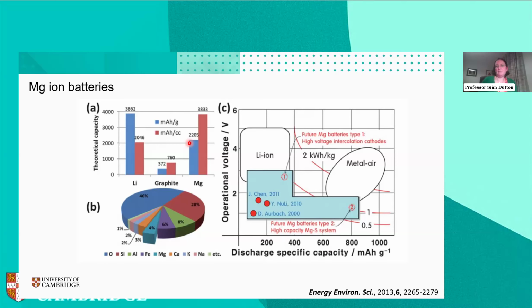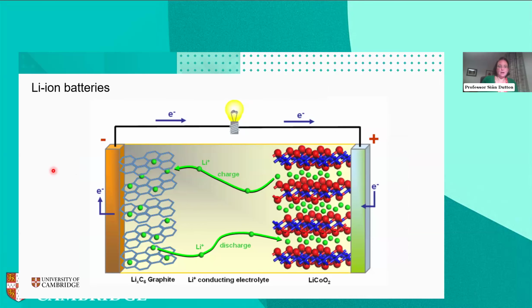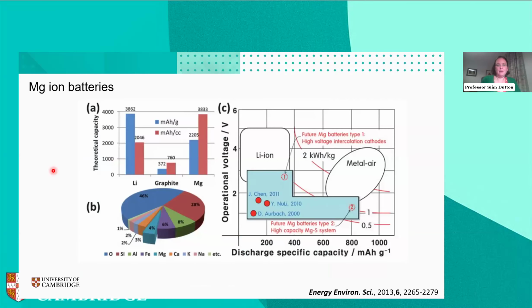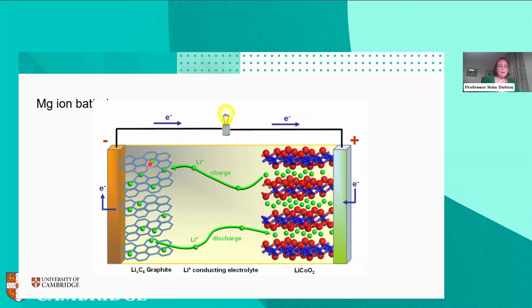Magnesium-ion batteries were first really reported by Doron Aurbach in the 2000s, and there's been a lot of work developing them since, really thinking about how you take these components from your lithium-ion battery and optimize them for magnesium. Here in Cambridge, we've been looking at this for quite a long time, and we've looked at replacing the graphite. Unfortunately, magnesium 2+ will not go between the graphitic layers. There's too much charge repulsion, so we can replace that with a magnesium bismuth antimony material, which will very readily incorporate magnesium at voltages equivalent to graphite.